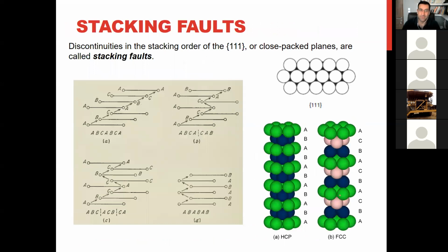So when you do that, you are making a stacking fault. Do you remember what the stacking is? It means A, B, C, A, B, C, A, B, C. But if you do like this, and the decomposition of this dislocation happens, you must have A, B, C again, but here, by the decomposition of the dislocation, you have A, B, C, A, C, A. It means a part of this converts to HCP. That we call a stacking fault.